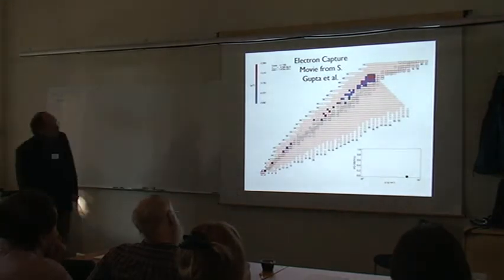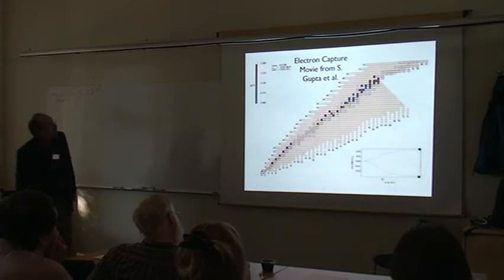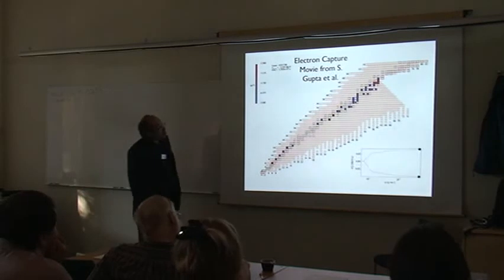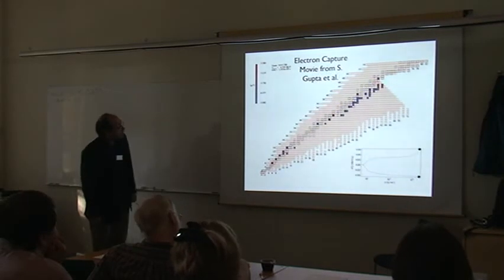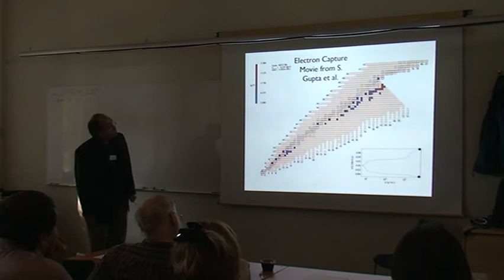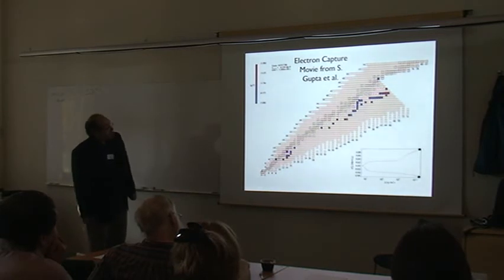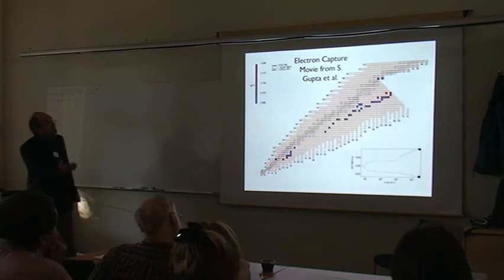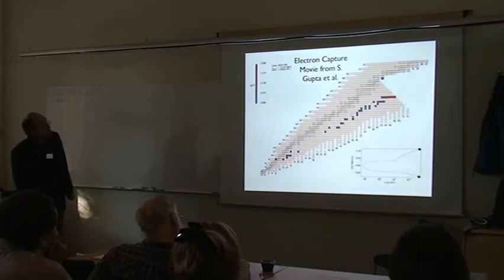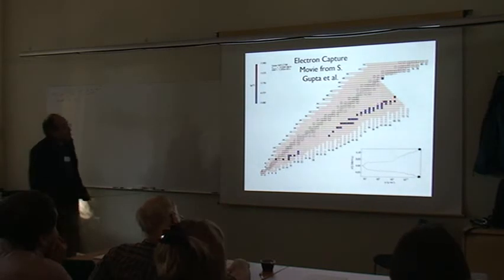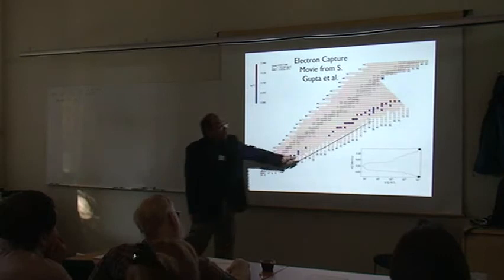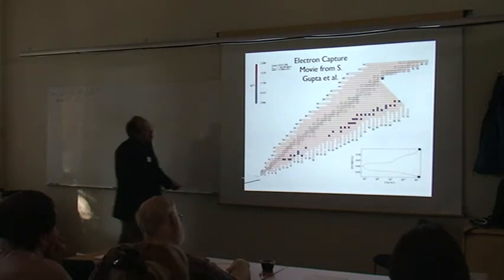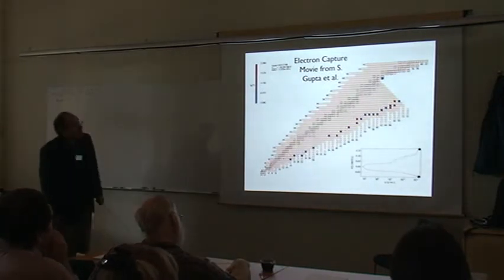So you're on the proton-rich side. And then we're just going to bury the material. As you bury it, it undergoes electron capture, and it marches along. Its density is increasing, and finally we reach a density of 10 to the 11 grams per cubic centimeter near neutron drip, and most of the material is now approaching the neutron drip line.